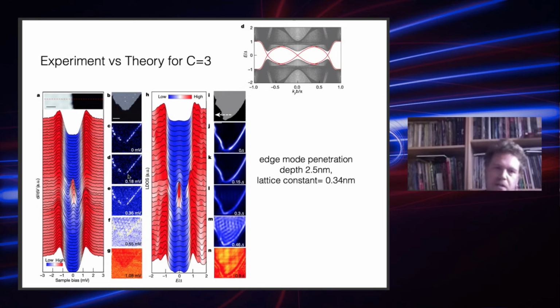And one thing that I want to emphasize here is that it doesn't really mean that there is a break in the edge mode. It's just that there is such a strong suppression of the signal that it drops below the sensitivity of the measurement. So it is always there, but you just don't see it because there is such a strong suppression and enhancement going on here.